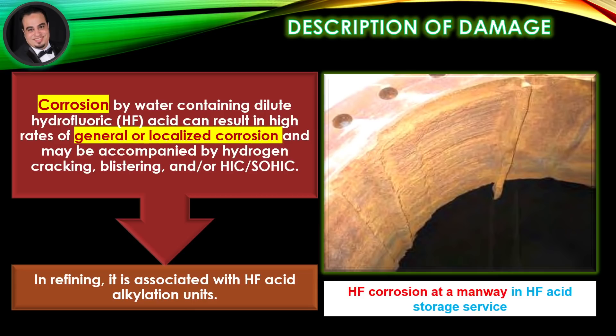Description of damage: Corrosion by water containing dilute hydrofluoric acid can result in high rates of general or localized corrosion, and may be accompanied by hydrogen cracking, blistering, and/or hydrogen-induced cracking, stress-oriented hydrogen-induced cracking. In refining, it is associated with hydrofluoric acid alkylation units, as illustrated in the figure.